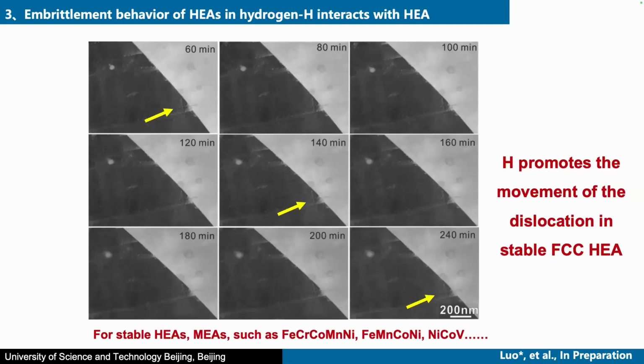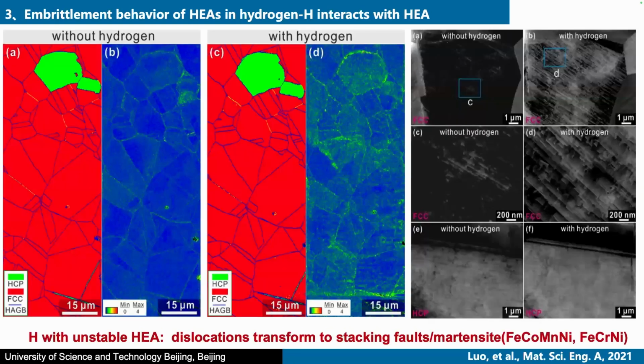And then the next step: if the hydrogen comes into the surface of the high entropy alloys, what can happen? Let's see. This is a stable high entropy alloy; there are many types. If we charge it with hydrogen and leave it for different times, we found the dislocations can only move from this side to that side, and no other phenomena can be observed. But if we did similar work on an unstable high entropy alloy,